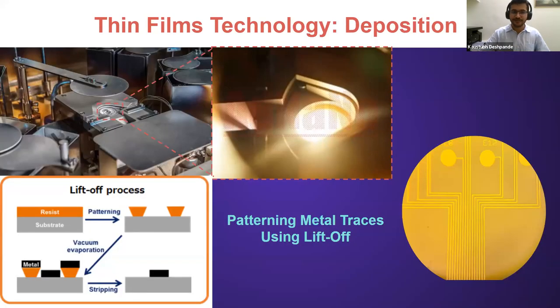Now, there are two ways you can proceed after doing lithography. You can either put down metal with deposition. It can be either physical vapor deposition or chemical vapor deposition. What we use is e-beam evaporation, and I'm just going to tease it a little bit, but it's a system where the machine is in high vacuum. It goes down to 10 raised to negative 6 torr.